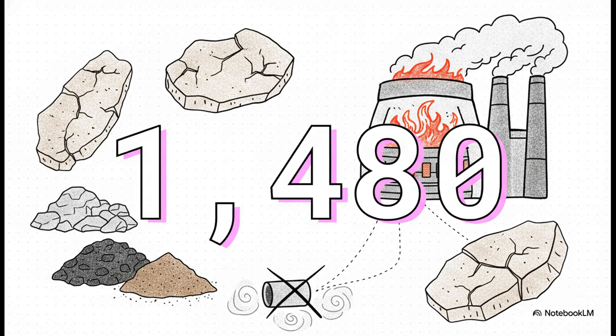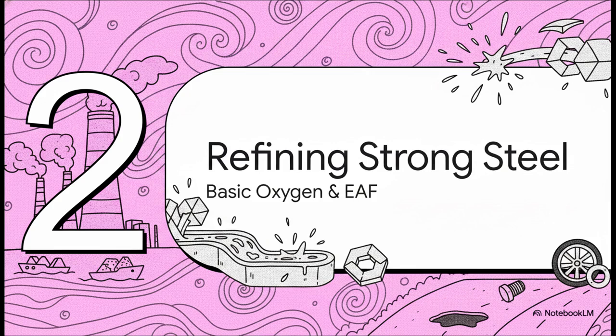But wait, before we can smelt this newly concentrated iron, we have another problem. Those fine particles have to be clumped back together. Otherwise, the dust would literally choke the gas flow inside a massive smelting furnace. We fix this through a process called sintering. We blend the fine ore with limestone flux and coke and heat it on a continuous strand to a blistering 1300 to 1480 degrees Celsius. This slightly melts the surface of the particles, binding them into a porous, mechanically tough chunk that is totally ready for the blast furnace. Moving right along to part 2, refining high-strength steel.